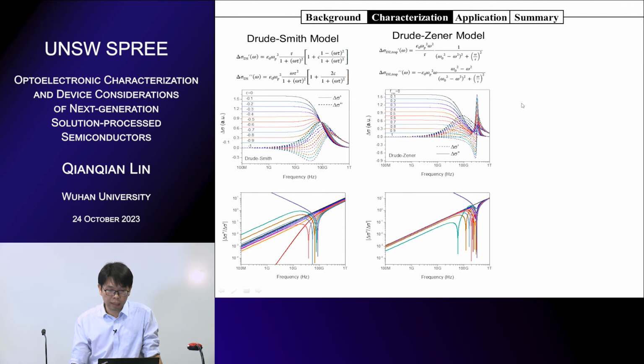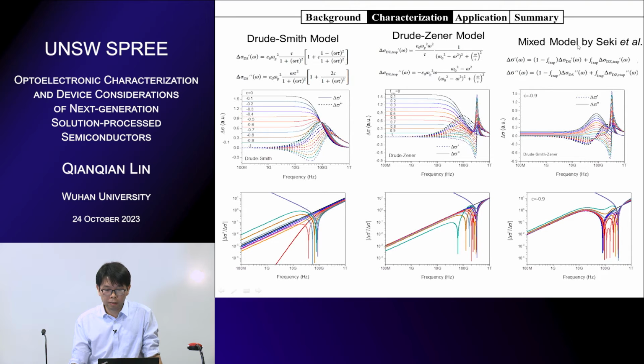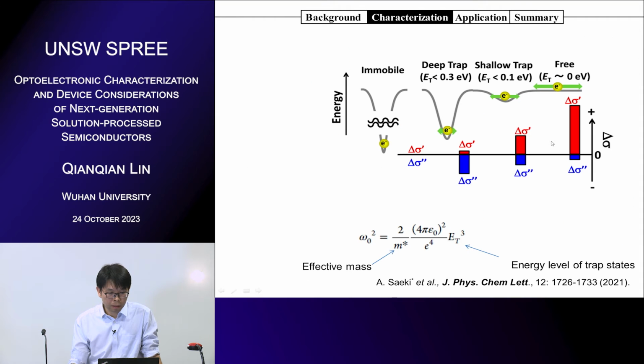You can fit the curves, and if you have traps, this model is proposed by Saeki, and the traps will also affect the spectra of the microwaves a lot. So if you look at the real and imaginary part of the conductivity, you can get the information of the levels of trap states. So from the decays, we get the numbers, but from the spectra, we can get the energy level. So it's different. We can get the energy level and also the effective mass of the carriers.